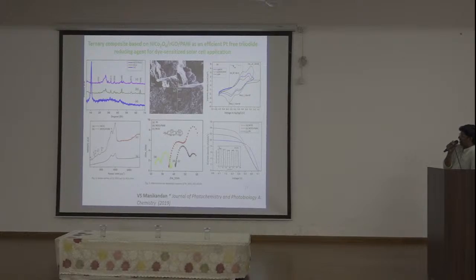We can see the nickel cobalt RGO composition is slightly decreasing the open circuit voltage. Normally, the VOC depends upon the Fermi level of semiconductor material like TiO2 and the potential difference with the electrolyte. So it is slightly reducing the fill factor compared to the platinum, but the short circuit current density is increasing because of the ternary composition.